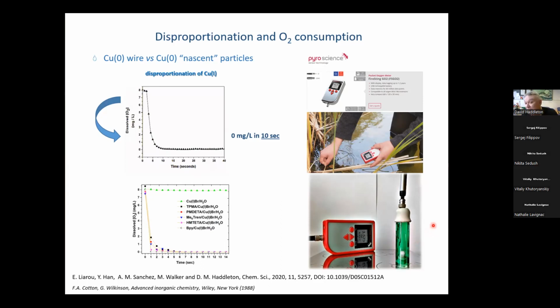And actually, we've not found an organic solvent that you can't put it in, really. And then when you do that, you will get this reading of the oxygen. So if you do that in the reaction that I was just showing you, the oxygen just plummets in 5 seconds, right? In 10 seconds, it's gone to less than 0 milligrams per liter. And then you can do all those different things.